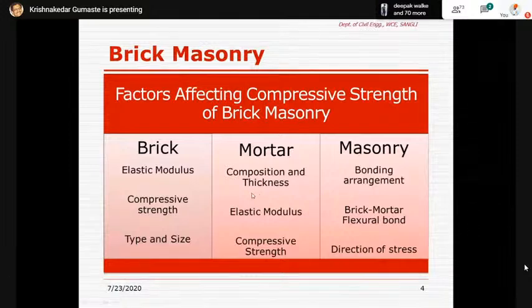And as the thickness goes beyond 12 mm, the strength of the masonry reduces, is what research has already shown. However, we are nonetheless very indifferent to the kind of practice that we do, that erratically the sizes of the bricks are different within the masonry. The sizes and the thickness of the mortar vary drastically from one end to the other within a particular wall itself, which are some of the sad facts. This is basically because, as I say, masonry has not been considered as a structural element.